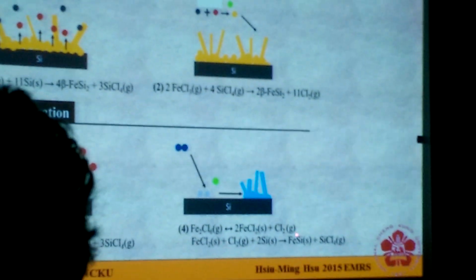And so the last question is how the nanowires grew. At low supersaturation, where the reaction concentration was low, beta iron disilicide was formed. At high supersaturation, iron monosilicide was formed.